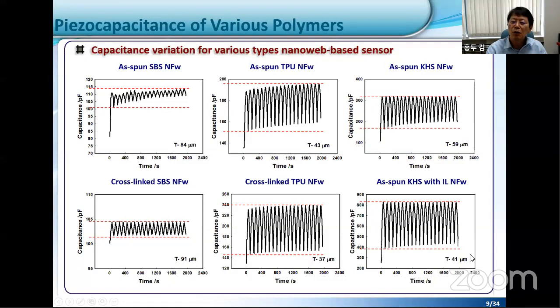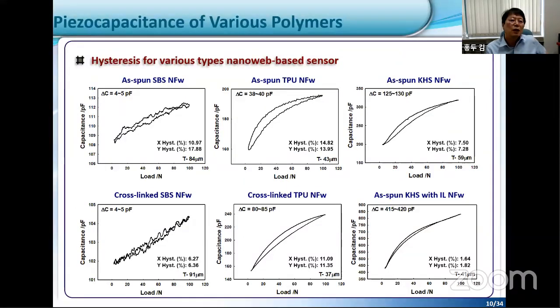We included a very tiny amount of ionic liquid, which is a very high dielectric constant material. If I include that, as you see, compared with the upper KHS versus KHS with ionic liquid, the difference in the capacitance is dramatically increased. So finally we found one of the best systems. If you take a look at one cycle out of the 20 total cycles, we can compare with the hysteresis of various types of nano-based sensors.